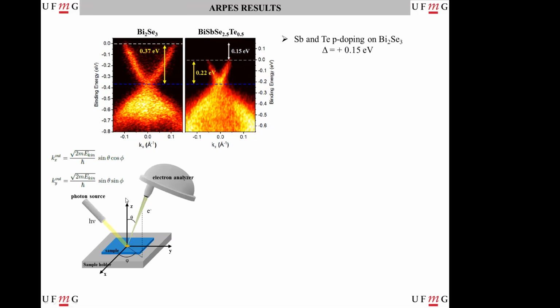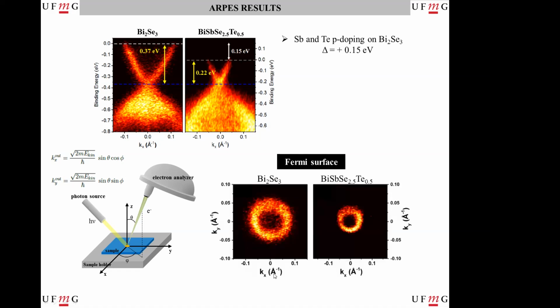Another thing that we can do using ARPES is that we can take this image of energy over a certain angle, but we can also rotate the sample and measure pictures at all different angles, and then we can take a cut here. For example, in this cut we have the momentum in both directions, like angle theta and phi, and this is a cut at the Fermi level with energy 0, and we have the momentum dispersion of each sample. When we do this on the Fermi level, we can retrieve the Fermi surface of the sample that we are measuring.